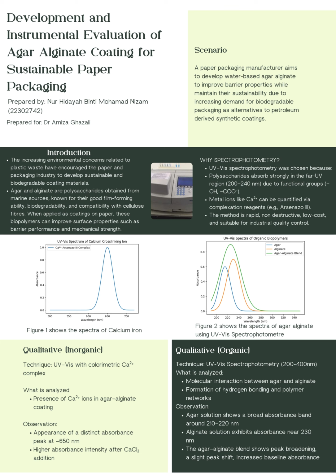First, for qualitative organic analysis, the extracted coating solution was scanned from 190 to 350 nanometers. Agar shows an absorption peak around 210 to 220 nanometers, while alginate shows absorption near 230 nanometers. When both polymers were blended, the UV spectrum showed peaks, broadening, and increased absorbance that indicate interactions and compatibility